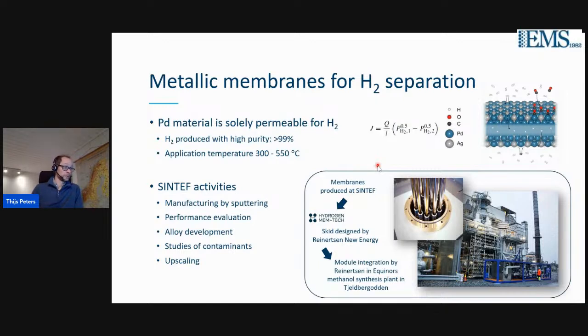We also work a lot on the performance evaluation of the membranes that we produce. One of the key points here is that a palladium membrane is normally not just a pure palladium membrane. It constitutes an alloy, and depending on the alloy concentration and the alloy type, you can tune the stability of the membrane, both in terms of thermal stability, but also stability against contaminants.